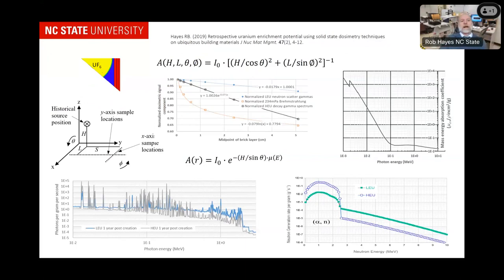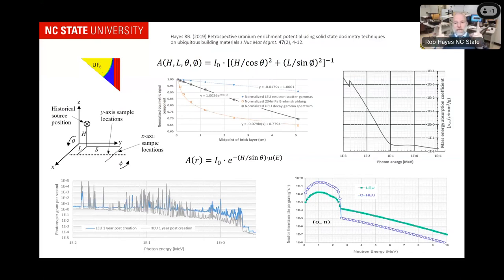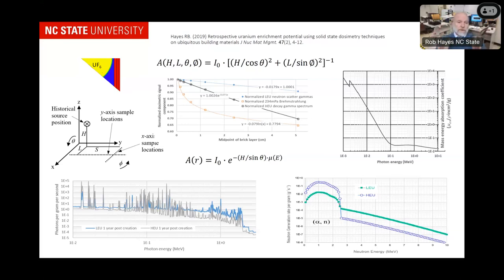Using that same theory with brick, now looking at uranium hexafluoride — published in the Journal of Nuclear Materials Management — using the same concept, based on the energy deposition profile you get from either highly enriched uranium (HEU) or low enriched uranium (LEU), you could discriminate the two. At a place like Natanz, using the dose-depth profile from different types, looking at both the alpha, the spontaneous fission, the Bremsstrahlung, and the gamma, you can empirically determine if somebody ever had highly enriched uranium at their facility, even if there are no longer any trace quantities of that uranium hexafluoride. The spectral measurement was made when the material existed, so you can look into the past for forensics — has anybody ever had HEU at this facility?